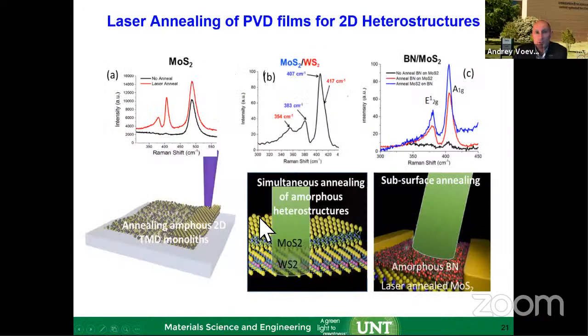All right, so moving on. If you're not doing a flexible substrate here, it was demonstrated that we can do molybdenum disulfide, and you can also do heterostructures. You can grow molybdenum disulfide and tungsten disulfide as a bilayer structure and anneal it. You can also anneal it under boron nitride, which is one wide band gap material. And this is now leading to the engineering of the entire device, where you can have a semiconducting layer.